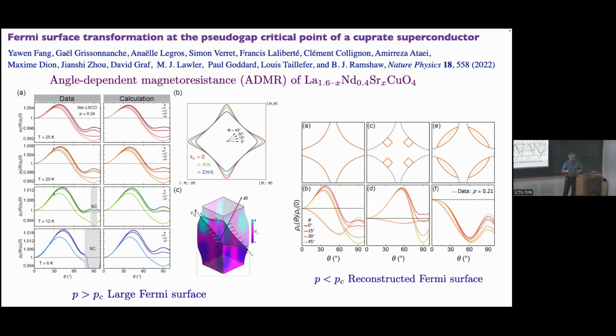So the answer depends very much on the kind of Fermi surface you assume. What you see here is data and calculation, and they agree beautifully using the large Fermi surface. This is on the overdoped side, where P is bigger than some critical P. On the other hand, if you go to P less than PC, then everything goes haywire.